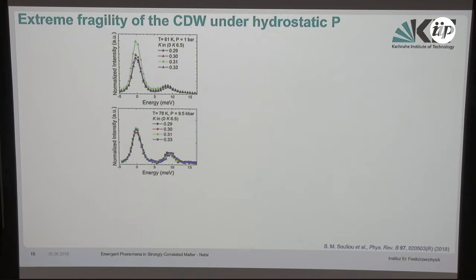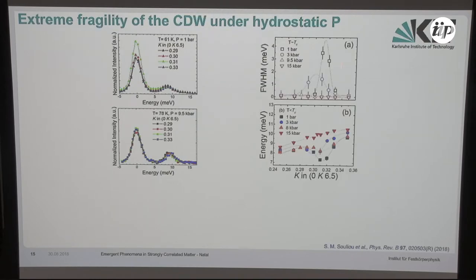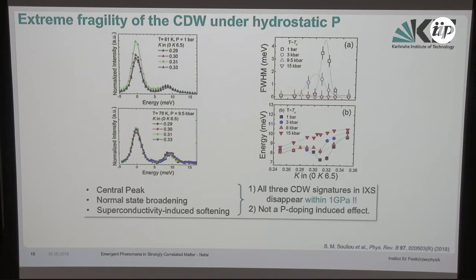Second and third, the line width, so the CDW normal state broadening of the phonon is suppressed with very modest pressure, I mean at 1 gigapascal, which is actually an annoyingly small pressure to work with in the diamond anvil cell. But at 1 gigapascal, the normal state broadening of the mode is completely gone, and the Kohn anomaly in the superconducting state is gone as well. So all three features that we had seen, the central peak, the normal state broadening, the superconductivity-induced softening, all three signatures of the charge density wave in inelastic X-ray scattering are completely gone by 1 gigapascal.